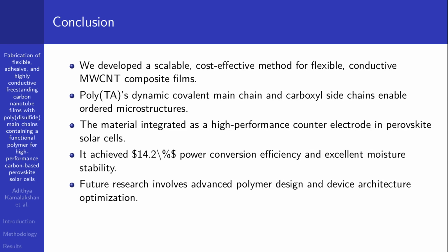In conclusion, our core contribution is the development of a scalable, cost-effective, and robust method for fabricating flexible, self-adhesive, and highly conductive freestanding multi-walled carbon nanotube composite films using a novel dynamic functional polymer, polythioctic acid. We have demonstrated that the unique synergistic interactions enabled by poly-TA's dynamic covalent polydisulfide main chain and carboxyl side chains lead to highly ordered, void-free microstructures, resulting in exceptional electrical conductivity and strong adhesion. This innovative material was successfully integrated as a high-performance counter-electrode in carbon-based perovskite solar cells, achieving a power conversion efficiency of 14.2% and excellent moisture stability, while simultaneously acting as a bifacial passivation agent for the perovskite layer.